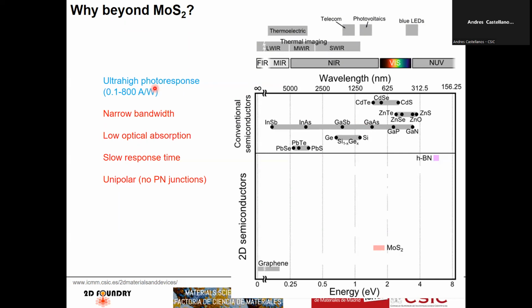So if we put all this together, molybdenum disulfide has this ultra high photoresponse that is cool, but it has a narrow spectral bandwidth. Also, molybdenum disulfide is a direct bandgap semiconductor only when it's a single layer, so that limits the optical absorption you can have in this material. And it's very slow because of the photogating effect. Moreover, it has an intrinsic N-type doping. For example, you might be interested in making PN junctions to build a solar cell. This cannot be done with molybdenum disulfide itself, so you have to play tricks.